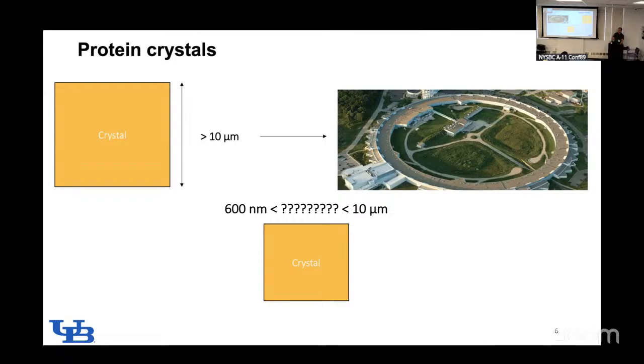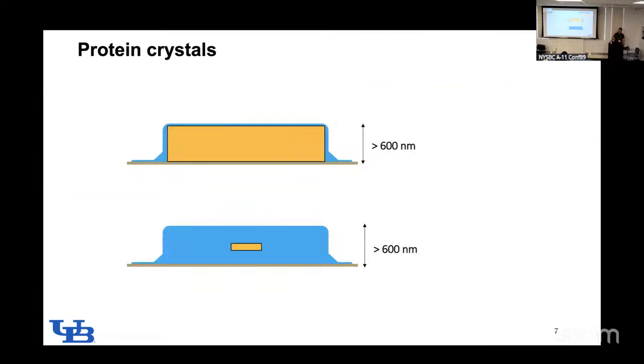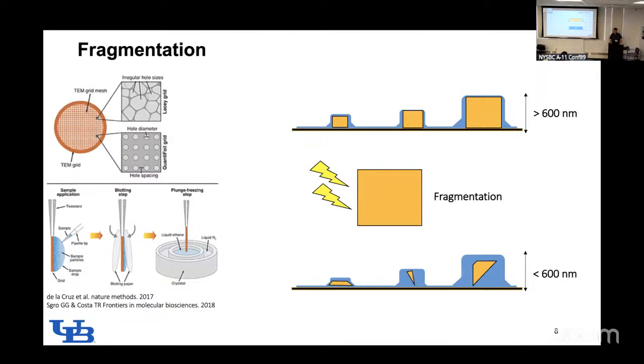So I spent a good amount of time trying to figure out what to do with that zone of pain. And very, very late in the game, I realized that this could happen 2 ways. I'm maybe a slow person when it comes to thinking. So to me, greater than 600 nanometers immediately meant I have a big crystal. Once I started working with membrane proteins, it became very apparent that we can have the case on the bottom, where I have a big pile of goop with a nanocrystal in it. These are identical to the TEM. It doesn't care. There's just too much stuff to get through. So either one of these is a big problem.